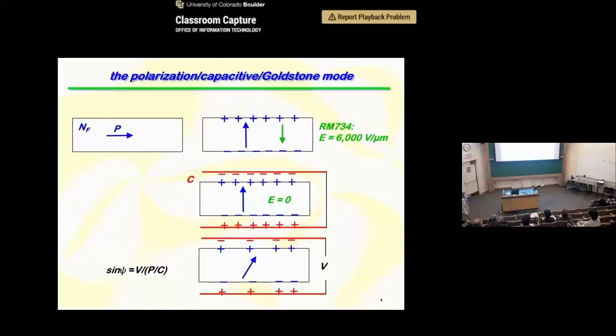So this means that if you actually apply a voltage across the electrodes, you can control the orientation of the polarization without ever having any electric field in the liquid crystal. You're only controlling the amount of polarization charge on the surface. So then the polarization will rotate more or less as a rigid block. The polarization is rigid because any spatial variation will end up producing space charge.